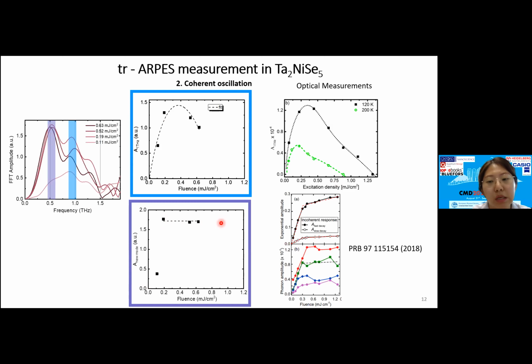It's similar to this current phonon dynamics. So we know there is no phonon mode at this range, and we can say this is an electronic coherent mode, but it behaves like a phonon in saturation. From this we suggest this is a polaronic mode, which is the lattice contribution to this mode.